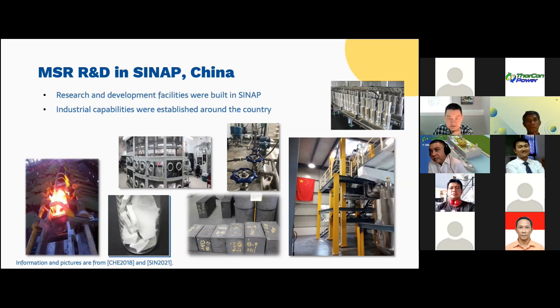So here is just a very simple example. They built a large glove box. There are multiple pieces of equipment like this in the institute. So it allowed them to do the salt chemistry, corrosion, and material studies. And then they got the molten salt loops, which you can actually start with a water loop and an oil loop. And this picture showing here is not a molten salt loop, it's an oil loop. It gives you the opportunity to study the thermal hydraulics.